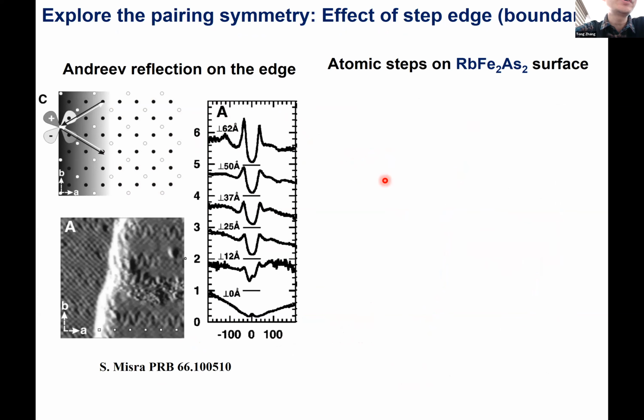So another way to get information on the gap structure is to check the response of the gap on the step edges. This is because if there's a sign change, if it's another gap with sign change, such as a D wave, and the step edge is facing the nodal direction, then the quasi-particle reflection at the edge will have a sign change. So in theory, that will give rise to an Andreev bound state, actually a zero bias peak. Now this is indeed observed on BSCCO, the cleaved surface. There are step edges, and you can see close to the edge, there's the in-gap state here.